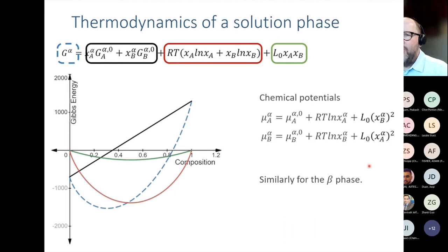In order to do so, I'd like to take a step back and remind ourselves how we model thermodynamics of a solution phase. This is for a liquid or a simple, straightforward FCC, for example. So in order to describe the free energy of that phase, we of course have a mixture of the two elements that we mix. It's just substituting one for the other. That's the black line in the diagram at the bottom.